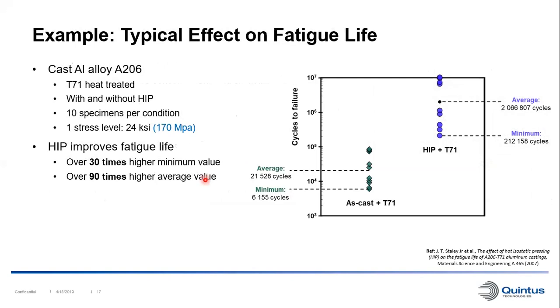And here we have an example of the typical effect of HIPing on the fatigue properties. On the diagram here on the right, we see fatigue data for a cast aluminum alloy, A206. This is a material that's been cast and then heat treated with a T71 treatment. We have variants with and without HIP. There were 10 specimens per condition that were tested at one stress level, 24 ksi. We can see the number of cycles to failure here on the y-axis. And on the left here in green, we have the material that has been cast and then heat treated, so no HIPing for these.